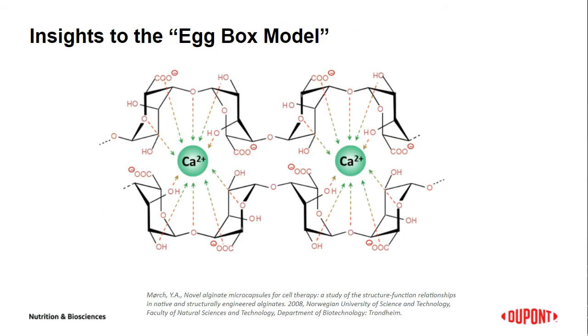Let's now have a look at the detailed structure of these junction zones, also described as the egg box model. This model describes a cooperative mechanism of binding between the buckled guluronic units, as a two-dimensional analog of a corrugated egg box with interstices in which the calcium ions are bound and coordinated. Based on the dimensions in the G blocks between the carboxyl and the hydroxyl groups, calcium ions are incorporated with high efficiency, whereas smaller ions like magnesium are not coordinated that well, and these form less strong gels.